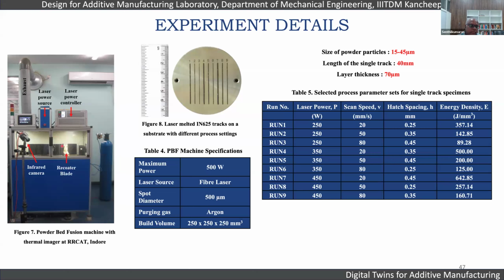So we utilized this particular machine because it has an infrared camera to capture the temperatures and also do some studies on the powder bed. This is the bed, SS316L. First, we started with single track experiments to characterize the prediction models of temperature. These are the different process parameters. We selected a DOE initially to minimize our number of simulation and experimental trials.